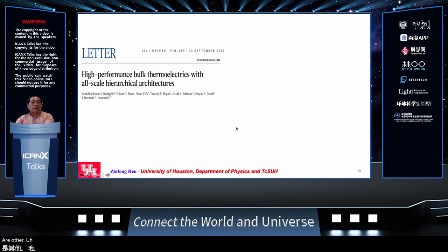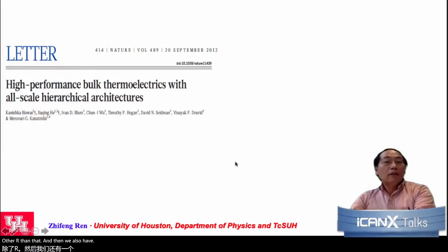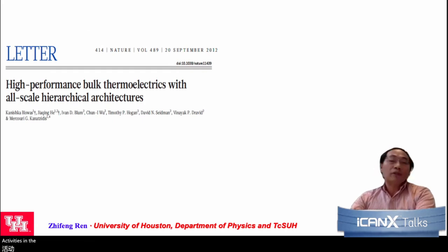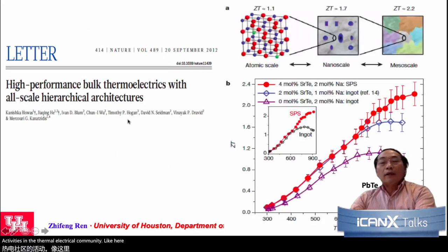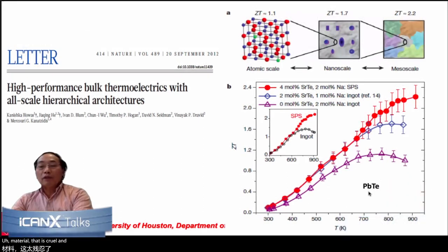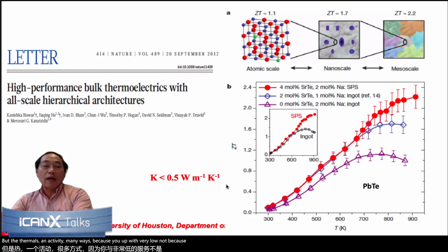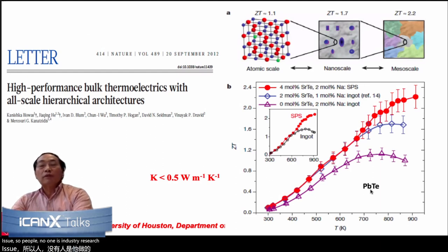Other than that, we also saw a lot of activities in the thermoelectric community, like here, Mercouri Kanatzidis's group, who demonstrated that lead telluride has very high ZT, above 2 at a temperature of about 600 degrees C. And that's very wonderful. But it is mainly because of the very low thermal conductivity, not because of the high power factor. And then later on, as we understand, lead is a toxicity issue. So people in the industry really don't want to bring toxic lead into large scale application.